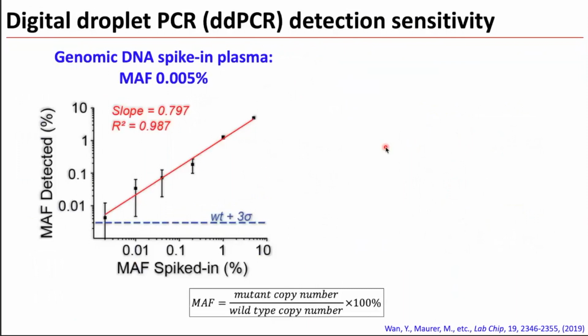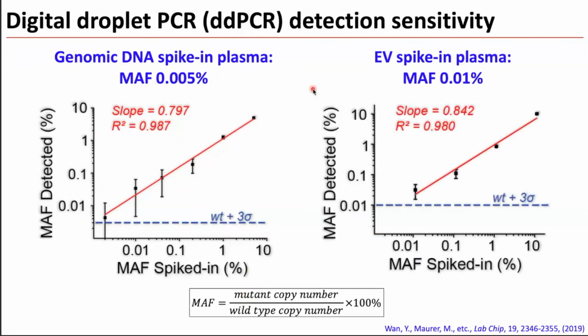And then for the detection, as we indicated, we need to improve the mutant allele fraction. So we adopted digital droplet ddPCR technology. What you see here is the x-axis is the spiking percentage, and the y-axis is the detection. Basically, for the mutant allele fraction, which is the mutant copy number versus wild type copy number, we can achieve about 0.005% if we spike genomic DNA directly into plasma. If we spike EV into plasma, it's about the same order of magnitude. We can achieve 0.01% mutant allele fraction.